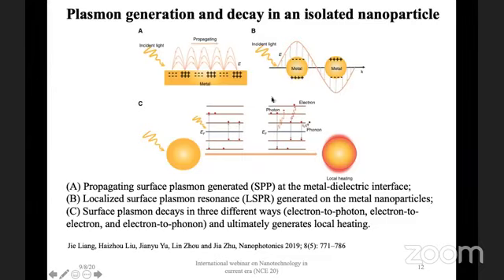Now, once we have plasmons excited in nanoparticles, there are three ways these plasmons decay. They cannot exist forever. There's always a decaying process, and number one, they decay by emitting a photon. Or they can excite another electron: the photon results in absorption, and then an electron is injected to a higher level. We call this a hot electron, and that's very important, and this is what we want to do. Or they can produce heat, so they can do local heating as well by producing phonons. So these three phenomena can happen. Most importantly, we need to have hot electrons coming from these nanoparticles when we have excited plasmons.